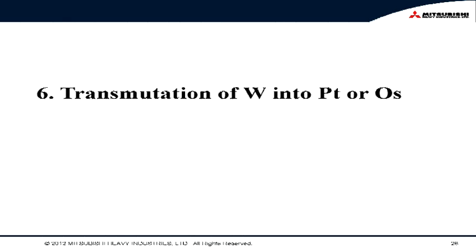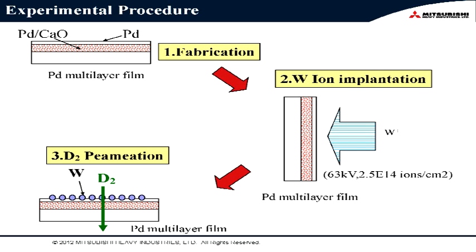Okay. So these are preliminary recent results of transmutation of tungsten into platinum or osmium. This is the experimental procedure of the tungsten experiment. At first, we fabricate the palladium multilayer thin film, and after that, we perform tungsten ion implantation. And we perform the D2 gas permeation experiments like this.